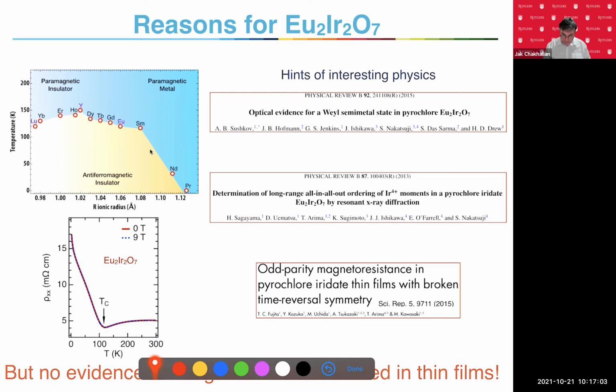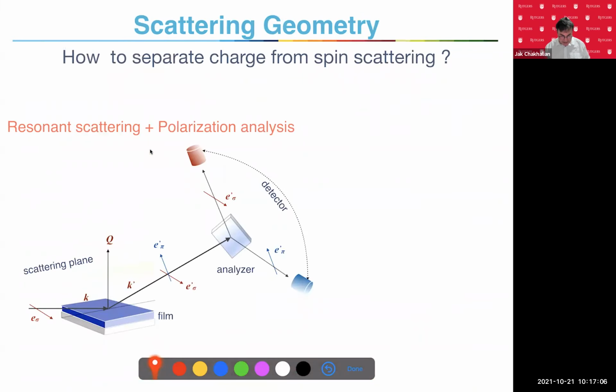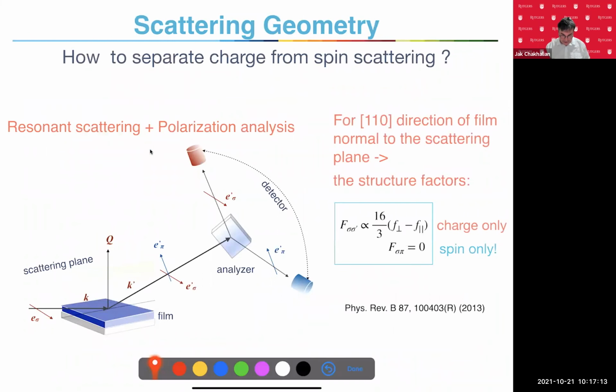So we took our film to the synchrotron with our collaborators at Argonne National Lab. They did some tricks, because it's very, very hard to distinguish magnetism in a thin film from just regular scattering, because you have charge and you have spin. So there is a trick. They invented a new trick doing polarization analysis of X-rays. If you polarize your light in this way, like this, and you analyze light like that, then you will see only spin. So the incoming light has polarization like that. Then after the scattering, you analyze it with the polarization like that. Then you detect your scattered light, X-rays, and then you will see spin only.